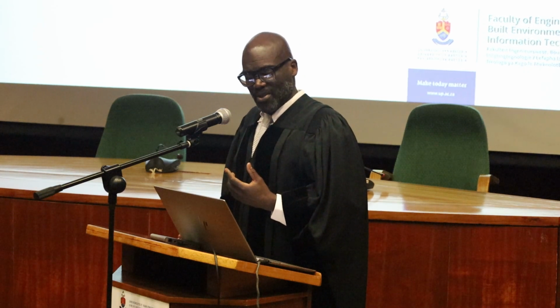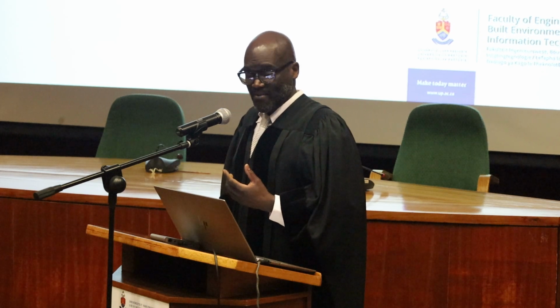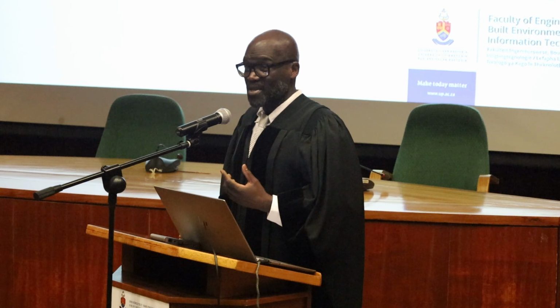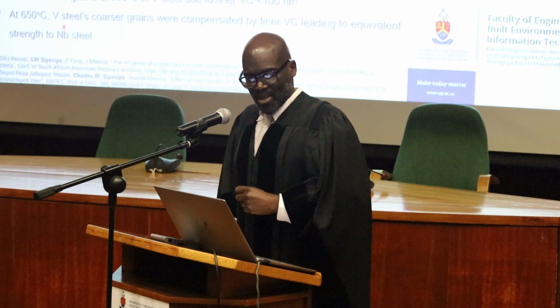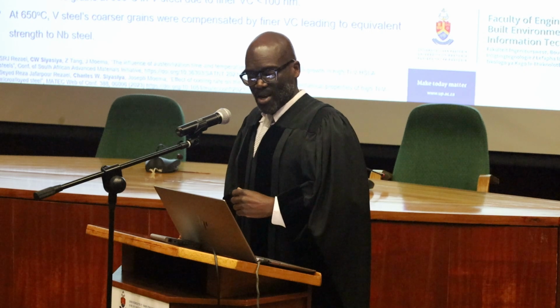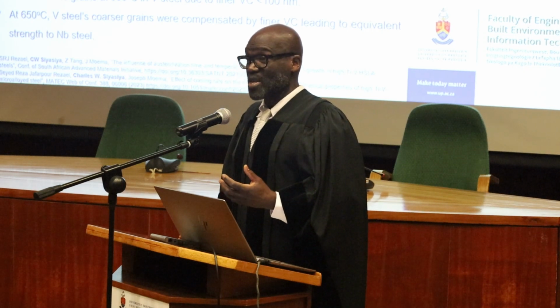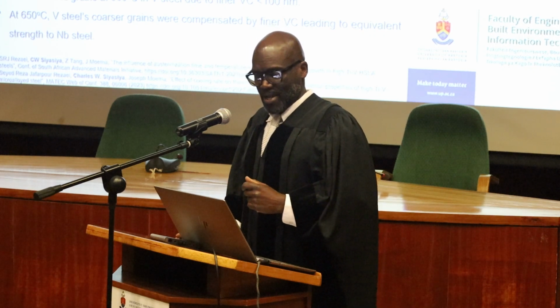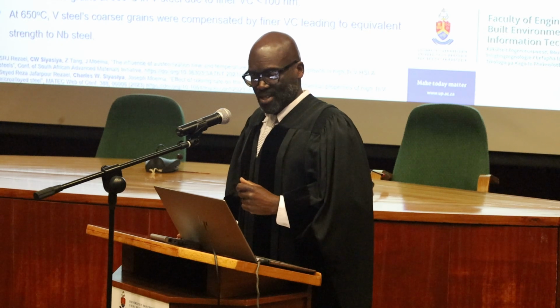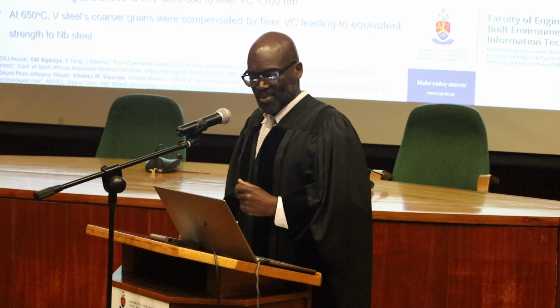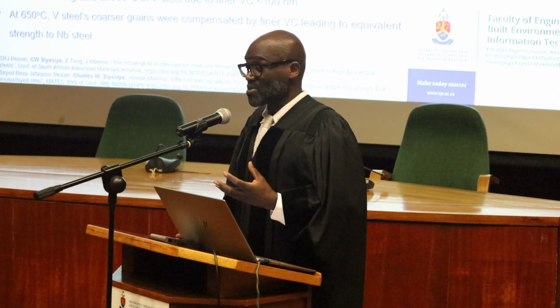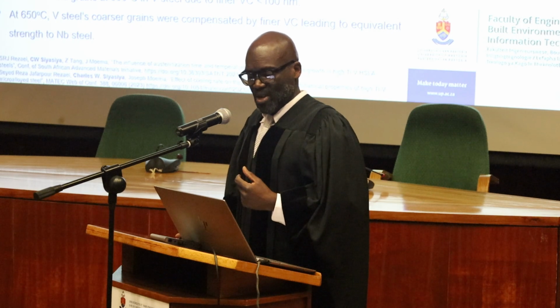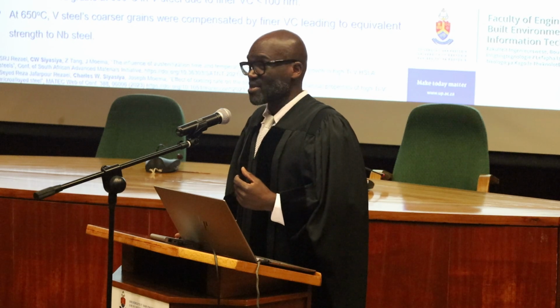As you may see here, for the niobium steel, the grains still remain fine, but for the vanadium, the grains are growing, which means not good properties. And to compensate for that, the fine vanadium carbides were able to make up for the loss in strength due to the coarsening of the grains. And the data that was used to generate these inverse pole figure maps was also used to characterize the substructure, and out of that it was possible to conclude that both steels at this coiling temperature are just partially recrystallized as measured by the low angle grain boundaries here.